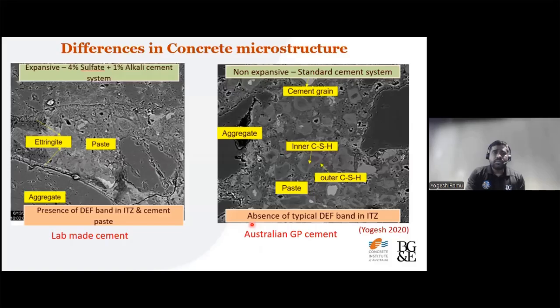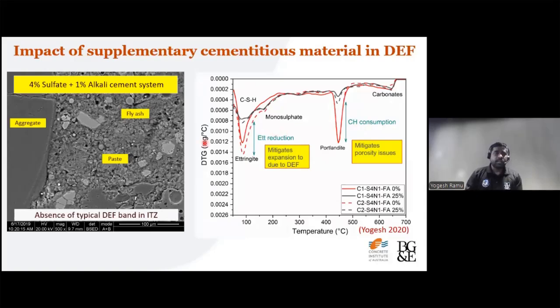I will talk you through some of the differences in concrete microstructure for these two cement systems. As you can see here, in the lab-made cement with high sulfate and alkalis, a lot of ettringite is precipitating between aggregate and cement paste, and also within the cement paste as well. Whereas in the non-expansive system, you couldn't see any ettringite precipitated at the cement and aggregate interface. So safe to say it doesn't have any expansive DEF in the system, but if it has fly ash, things are much better.